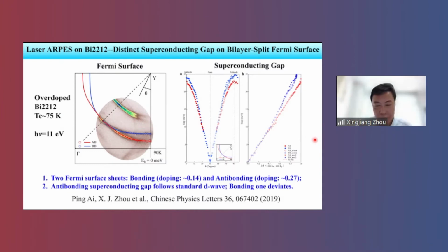By using laser ARPES, we can really see something we could not see before, and we can do something we could not do before. Previously, people already observed the bilayer splitting in bismuth 2212 because it has 2 copper layers. That means it has 2 Fermi surfaces, the bonding Fermi surface and the antibonding Fermi surface. But for a long time, people didn't know whether the superconducting gap on the 2 surfaces is the same or not. By using our laser ARPES, we can measure very precisely the superconducting gap of the 2 Fermi surface sheets. We can see the bonding and antibonding Fermi surfaces have different superconducting gaps. The difference is small, only about 2 millivolt, but you can see it.